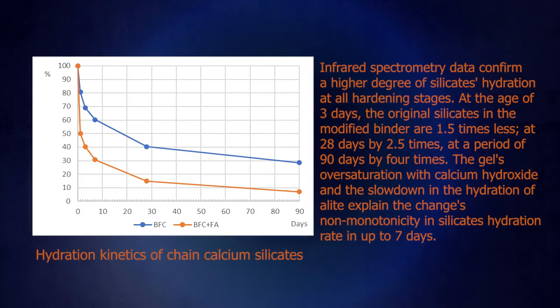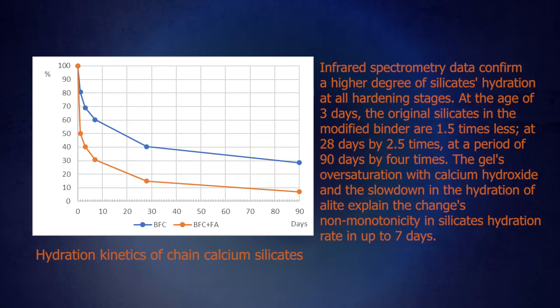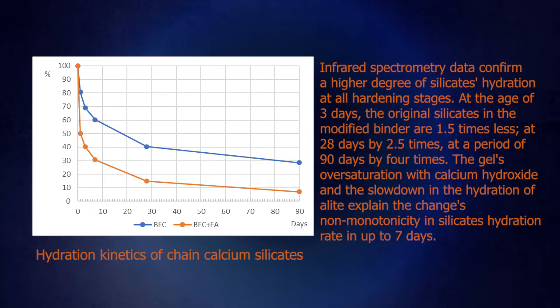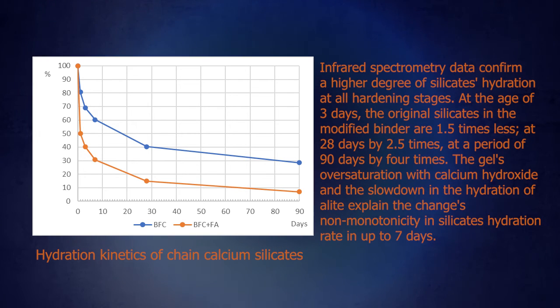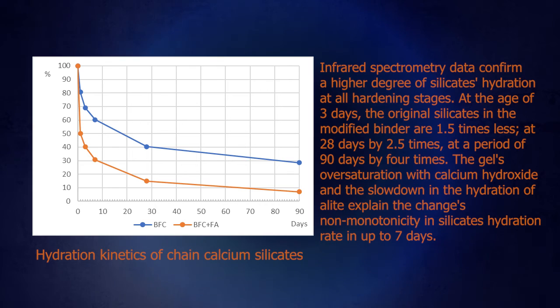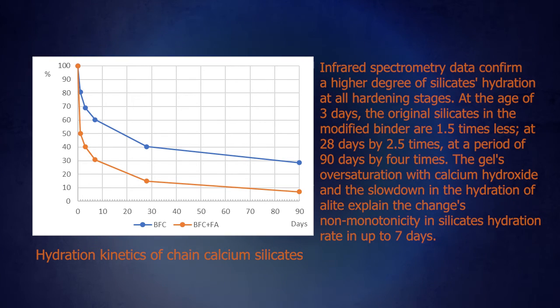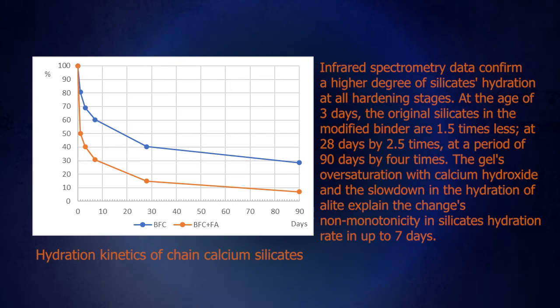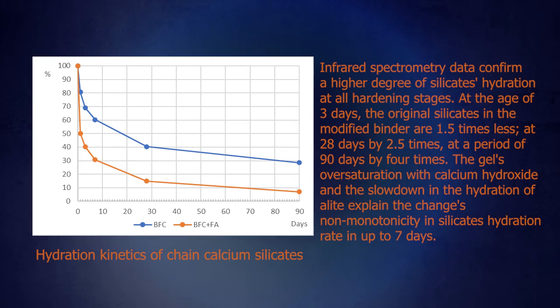Infrared spectrometry data confirm a high degree of silicates hydration at all hardening stages. At the age of 3 days, the original silicates in the modified binder are 1.5 times less, at 28 days 2.5 times, and at a period of 90 days 4 times. The gel's oversaturation with calcium hydroxide and the slowdown in the hydration of alite explain the non-monotonic changes in silicates hydration rate up to 7 days.